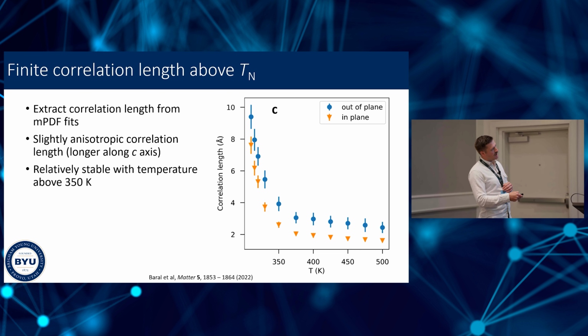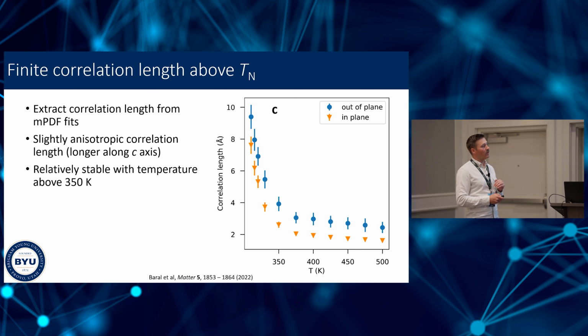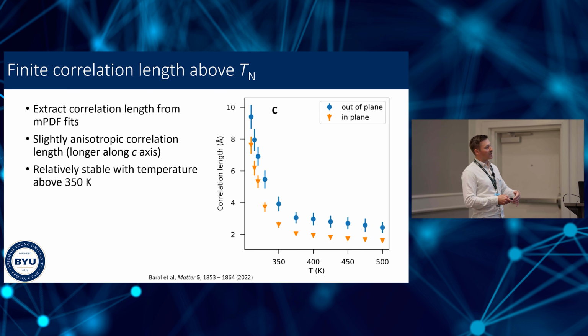But clearly you can see here that below about 350 Kelvin, there's a rapid increase in the correlation length as we are approaching the long-range ordering temperature. Above 350 Kelvin, we have relatively short-range but stable magnetic correlations, persisting up to the highest temperature we measured, which was 500 Kelvin.